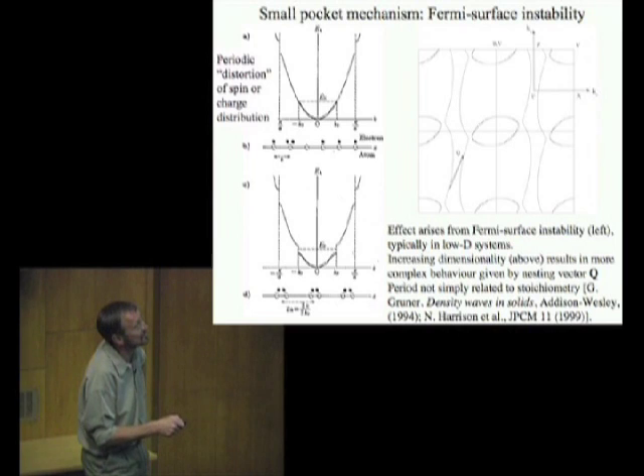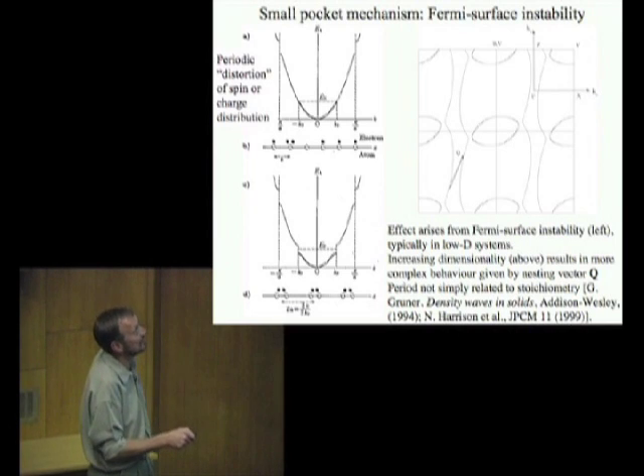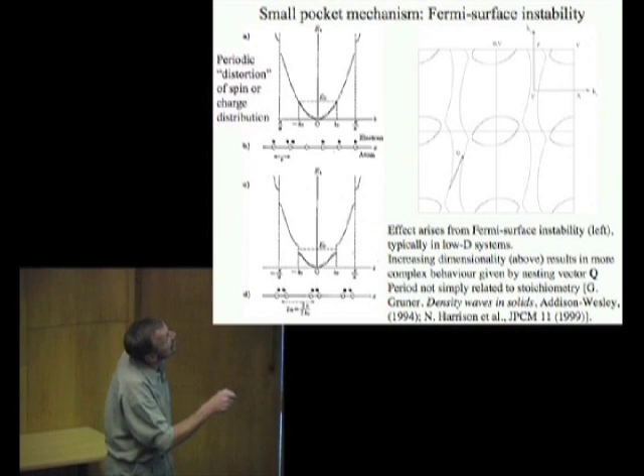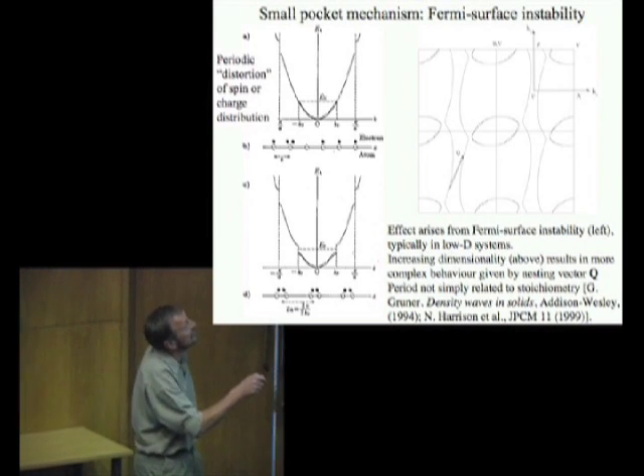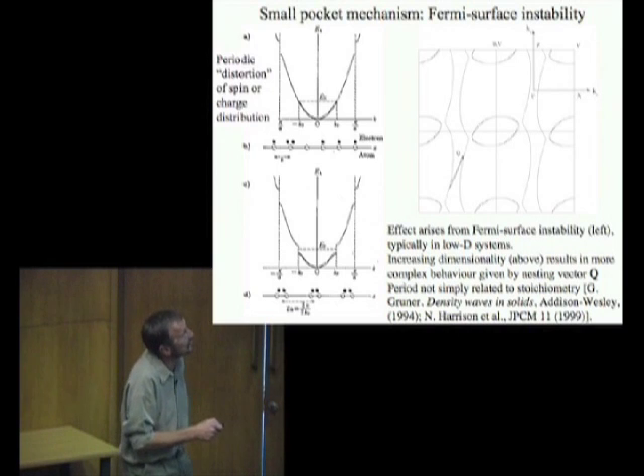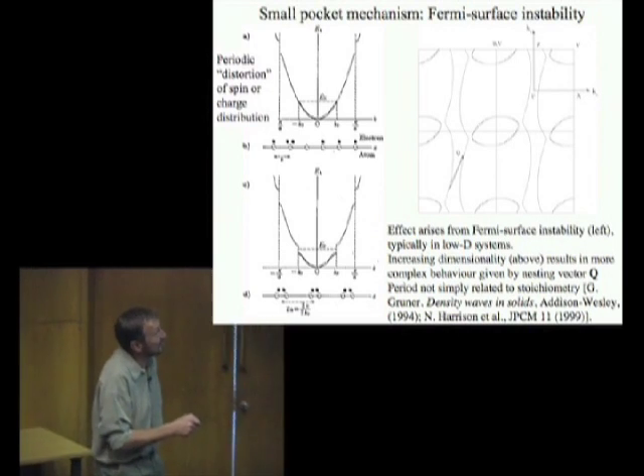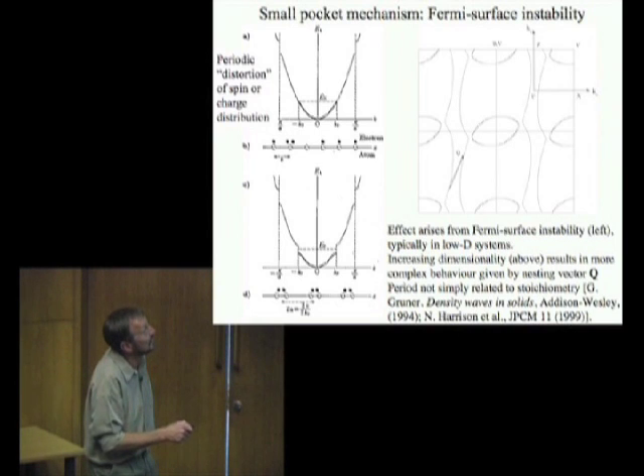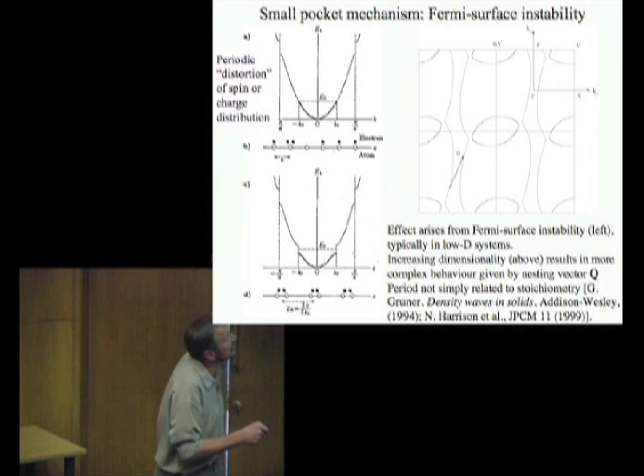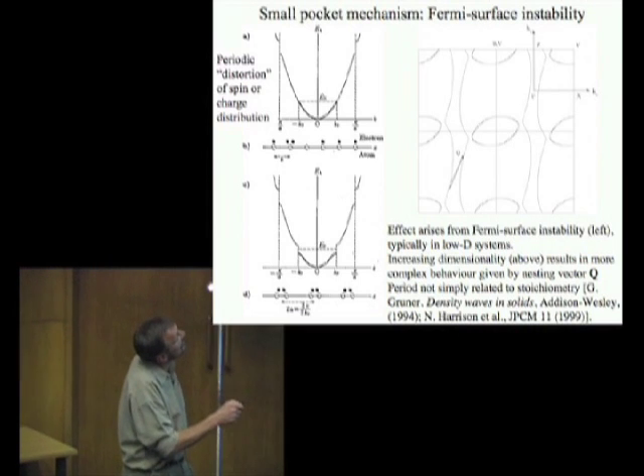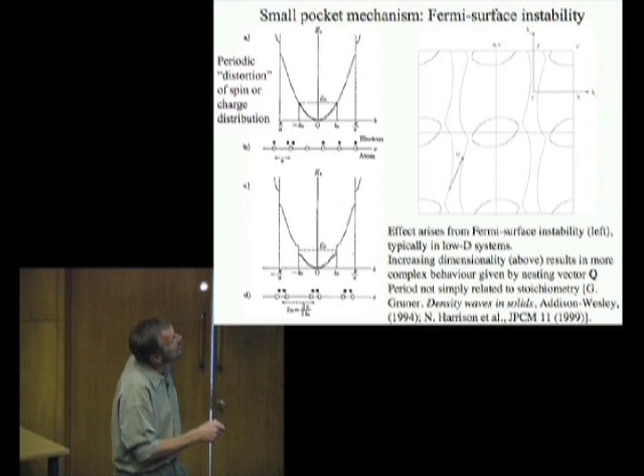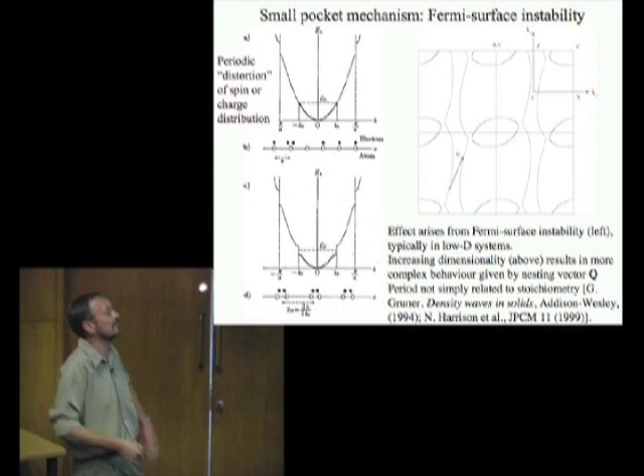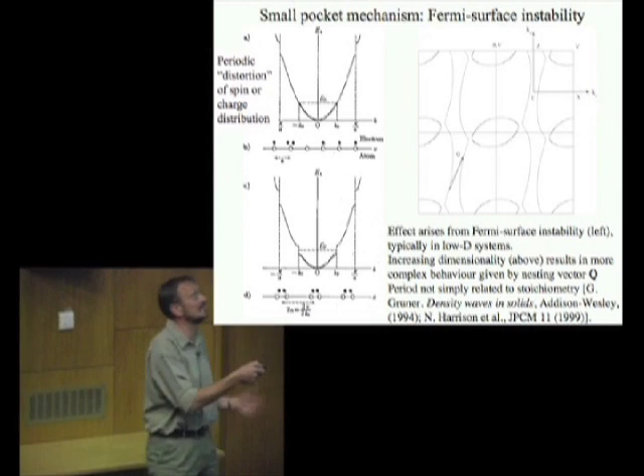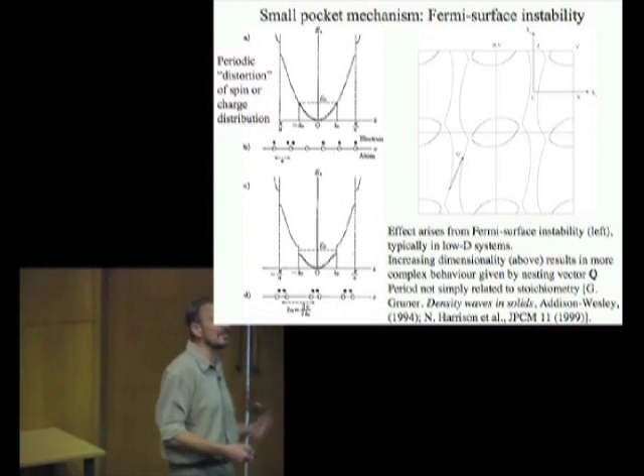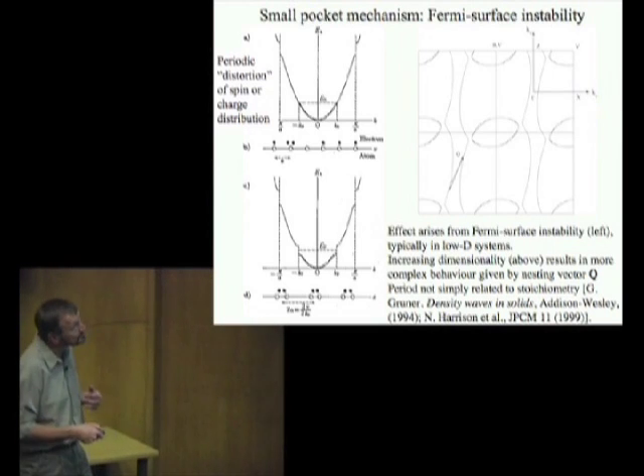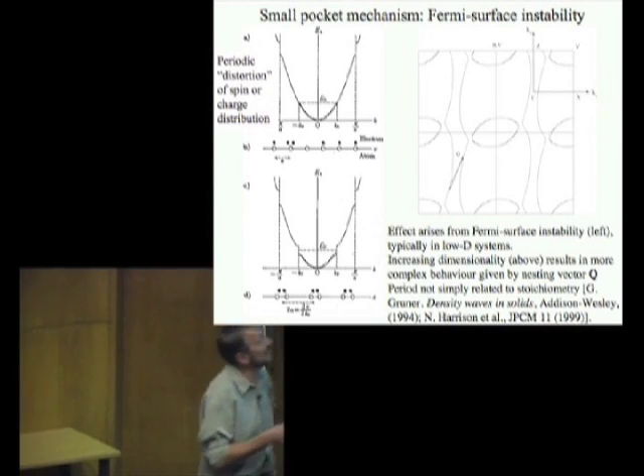Supposing it does a distortion like this, it now has a new periodicity in real space. Notice that the size of the unit cell in K-space is given by 1 over the size of the unit cell in real space. So we make a smaller unit cell in K-space. That has the effect, from elementary solid-state physics, of opening up a gap on the Brillouin zone boundaries due to Bragg reflection. And what's happened then is that all of the electrons that were populating this lower band have managed to lower their energy because of the opening of the gap. And this is actually a stable thing. This mechanism means that one-dimensional metals cannot be metallic at absolute zero. They're all insulators. But it also happens in more complicated systems as well.